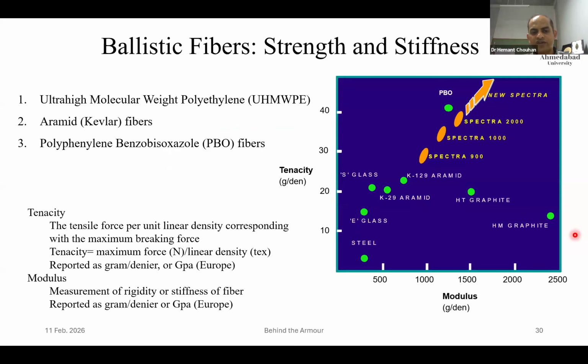The backing side of it, that is the soft side, is ultra high molecular weight polyethylene, and before that it was Kevlar. PBO is a very good fiber. It came up as a game changer, and very soon it was observed that environment is an enemy to it, so it won't last long. Whereas when you make a bulletproof, it should survive for at least 5 years.